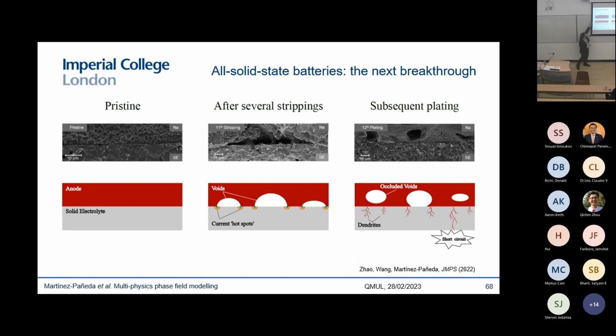You can see that initially you have the lithium metal and the solid electrolyte, and then every time you discharge the battery, you have stripping. So you are removing lithium from the anode, and therefore you have these voids originating in the lithium anode. And every time you charge, you have plating, so you're depositing lithium, and therefore you're shrinking these voids, and you are often isolating them from the environment. Being able to capture this voiding process precisely is quite important, because near the edge of those voids, you have what we call current hotspots, which are regions of localized, very high currents, where plating is exacerbated and dendrites form and grow.